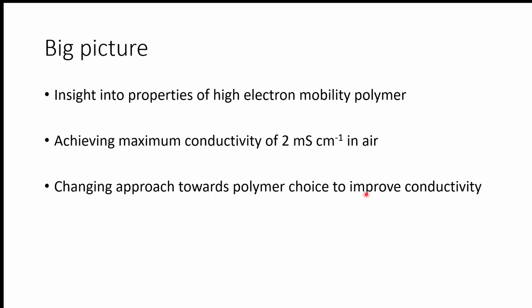Now, what is the big picture of this? What we were able to learn is insight into the properties of the high electron mobility polymer. And then we were able to achieve a maximum conductivity of 2 millisiemens per centimeter in air, which was pretty satisfactory for what we wanted to do. This allowed us to change our approach to which polymer we wanted to choose. So now we want to opt for polymer systems that are maybe not necessarily as flexible, or that might have different miscibility properties, to get different conductivities.